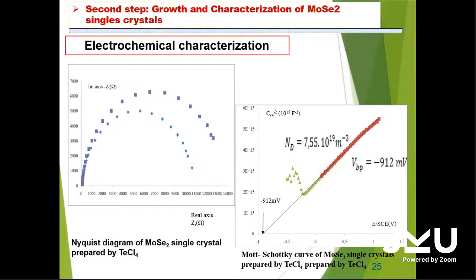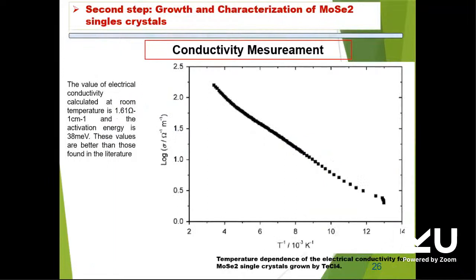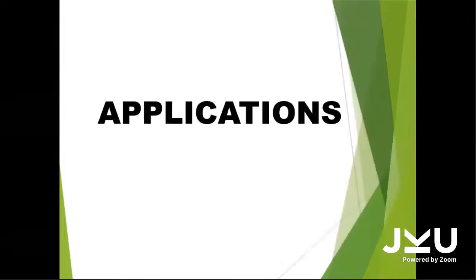Finally, the electrical conductivity value made it possible to identify the activation energy and the electrical conductivity. The values obtained are in agreement with what was found in the literature. These results made it possible to use the material for different applications. So after the material characterization, we use them for different kinds of application.